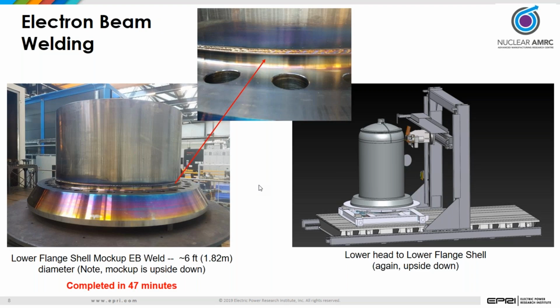This is an electron beam weld that we've done as one of the mock-ups in the small modular reactor program. Again, this is about a 6-foot diameter vessel. The flange is a little bit larger than that. We've been able to complete this weld in about 47 minutes. That's a real game changer, if you can perfect this technology to where you can apply this time and time again, and that's what we're currently working on.